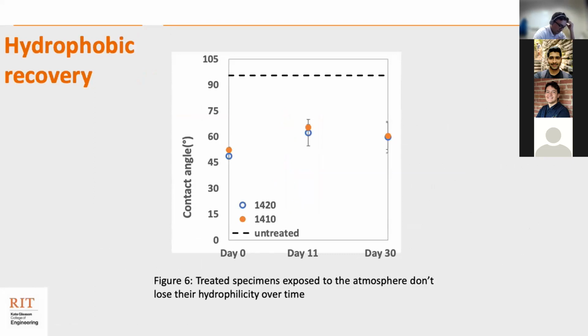Previously, researchers have shown that plasma treatment suffers from something called hydrophobic recovery, which means the plasma treatment tends to wear off after being exposed to the atmosphere. So we tested that to see if our films suffered from the same. This was done by plasma treating these samples for 10 and 20 seconds and measuring the contact angle over a period of 1 month.